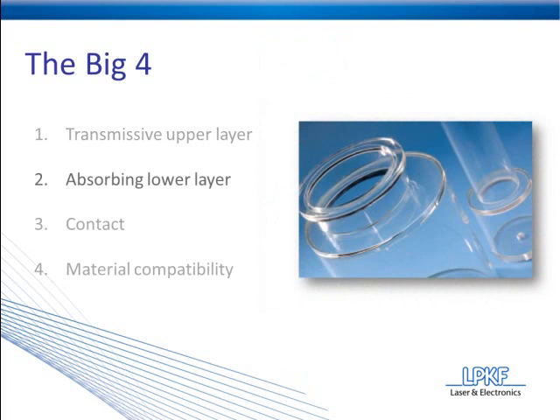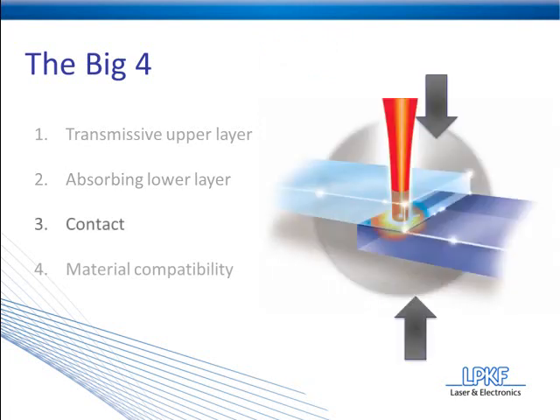So that brings us to factor number 3, which is contact between the 2 joining partners. Now it does sound relatively obvious that if you're welding 2 pieces of plastic together that they would need to be in contact, but there is a less conspicuous reason that we bring this up. Now recall that the laser radiation is absorbed by the lower layer, and this absorption creates heat. Now it's this heat that allows the plastic to become molten and create a weld.